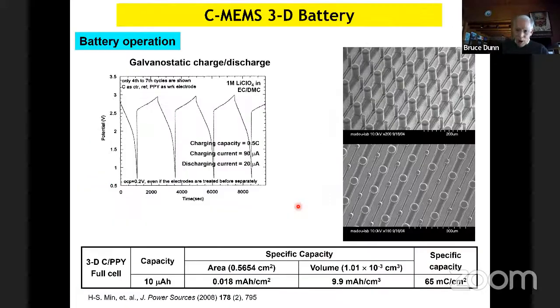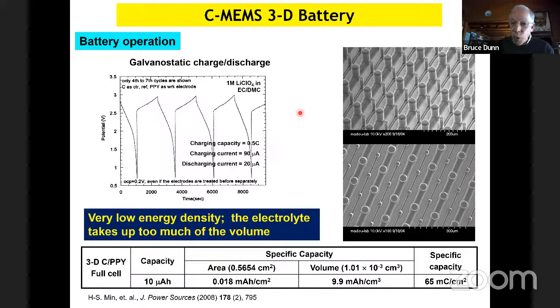It works. There's problems. First of all, there's soft shorts, and that's what this one shows over here, because not all the arrays stand up. There was no separator, and so some of these would fall over and you get a soft short. But the other issue, which is actually much more important, is that you have way too much volume devoted to the electrolyte. What we learned from this system, when we determined the capacity of what we should have and what we were getting, was really, really low capacities. Because of that, we recognized that, oh my goodness, the electrolyte is taking up way too much of the volume. We've got to do something else.